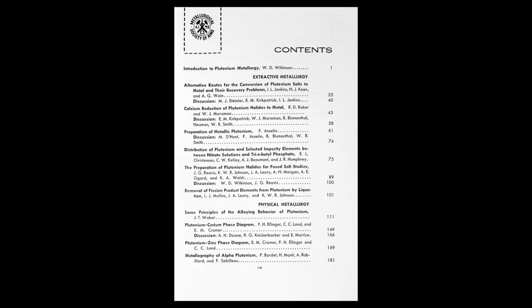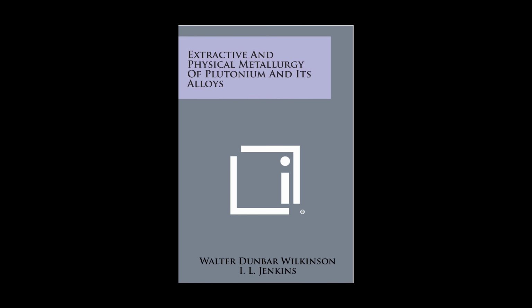That's remarkably clean, especially given all the challenges we talked about earlier. What kinds of impurities were typically left behind, even in trace amounts? Table V gives a pretty detailed list. You'd find traces of lighter elements, lithium, beryllium, boron, also some common metals like sodium, magnesium, aluminum, potassium, calcium itself, iron, manganese. And non-metals like carbon, oxygen, silicon were in there too, in small amounts. But despite all those trace bits, the overall plutonium purity was consistently better than 99.8% by weight. Still, incredibly pure, all things considered.